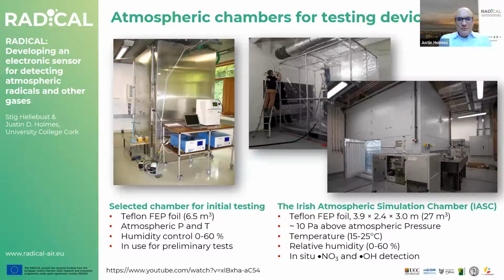So these are the chambers that we are working on at the moment. On the left is the atmospheric chamber that we're using to test our current devices. It's about 6.5 meter cube volume, under atmospheric pressure and temperature. There is some control of humidity, and it's a good chamber for our initial tests. There is also the Irish atmospheric simulation chamber in Cork, which is a much bigger volume chamber. You have better control over temperature and humidity, and you can generate nitrate and hydroxyl radicals in situ.